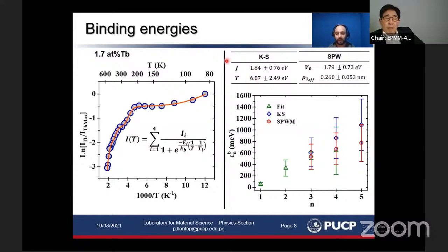So with these parameters calculated, we further calculated also the corresponding binding energies for the cluster with 3, 4, and 5 ions. As you can see, those in green are the experimentally obtained binding energies, and those in blue and red are from the Koster-Slater and the spherical potential well model. For those with 3 and 4 ions in the cluster, we can see that the experimentally obtained values are in good agreement with the ones calculated with the model.